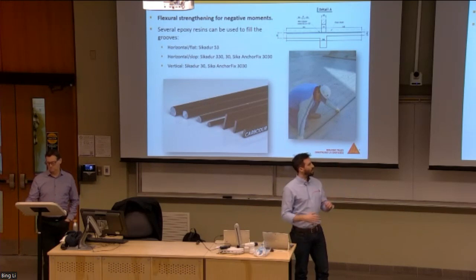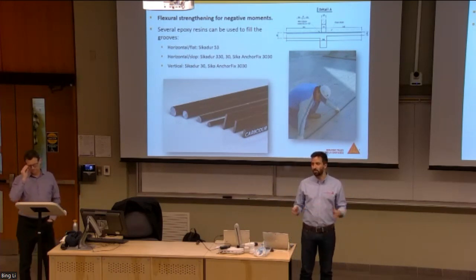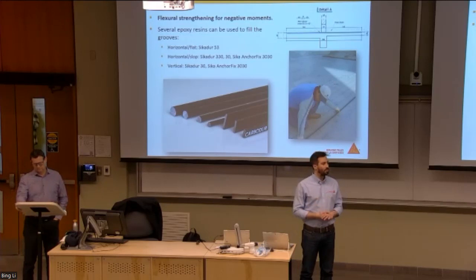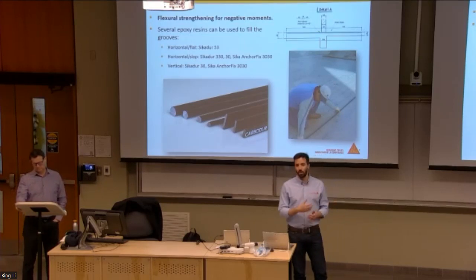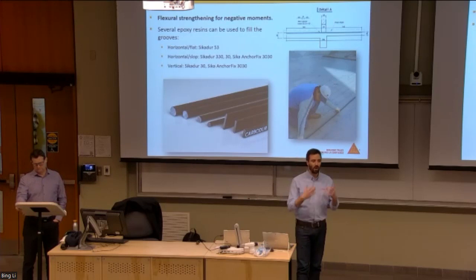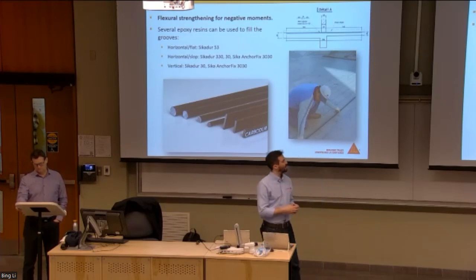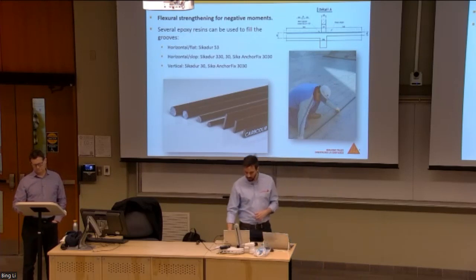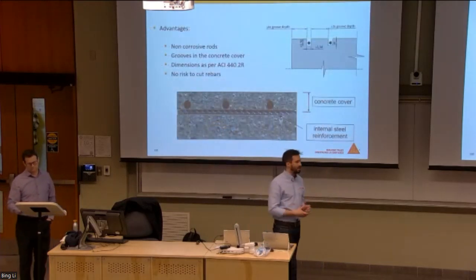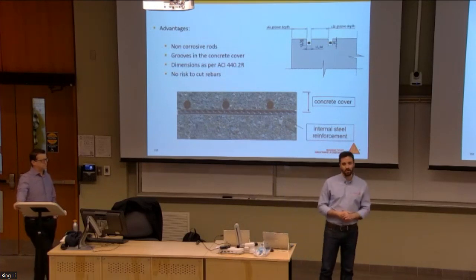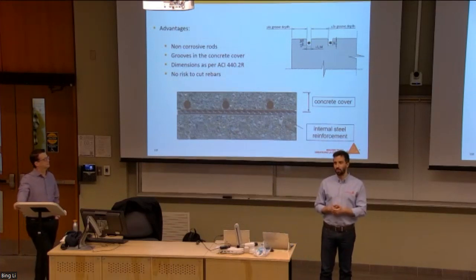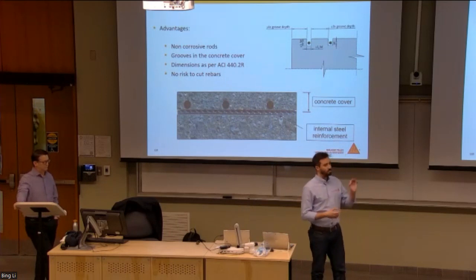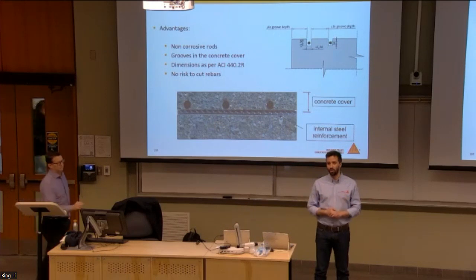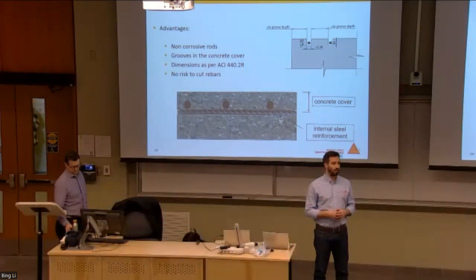If you are working with a small slope on a horizontal surface, it's better to have a more thixotropic material. So we have resins for that. Same thing if you are working on a vertical surface, if you want to stitch some cracks, for example, on a concrete wall. So quickly, the advantages of this solution. FRP materials are non-corrosive compared to steel. That's the reason why we can put them in the cover of the concrete. They are not going to be affected by the corrosion process.